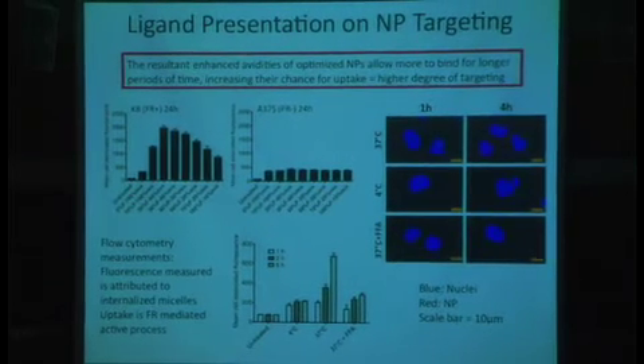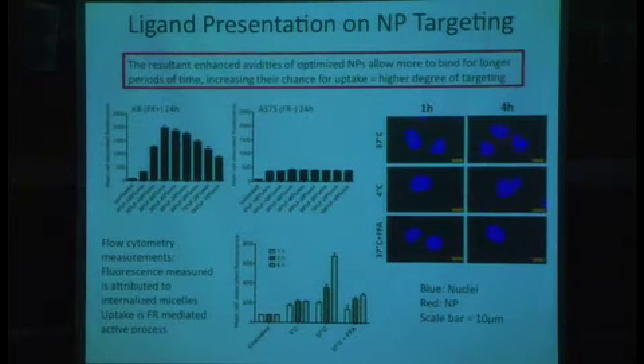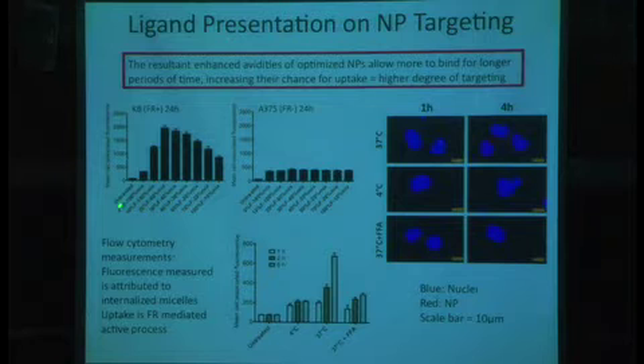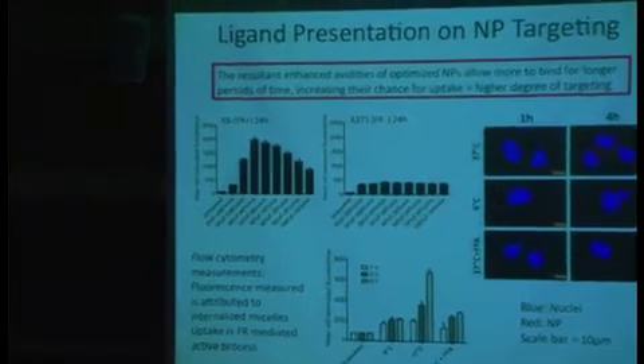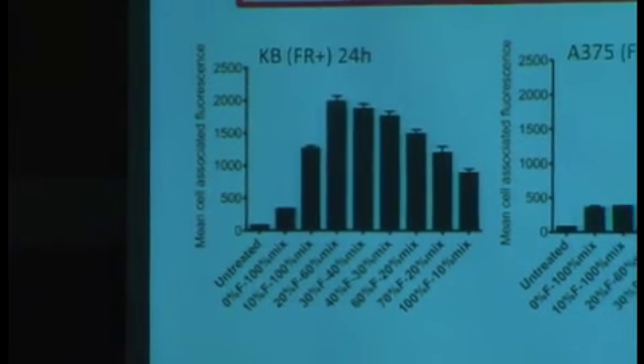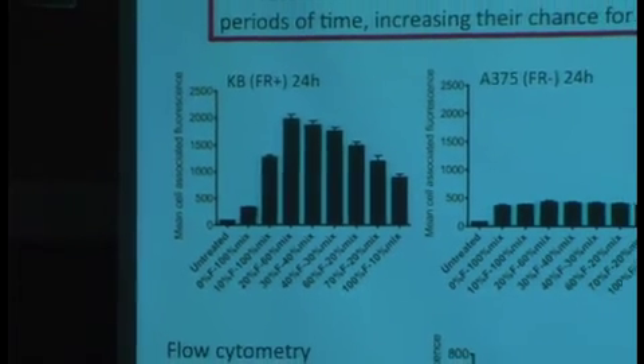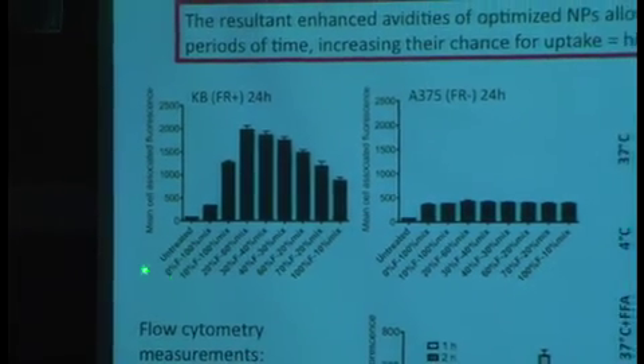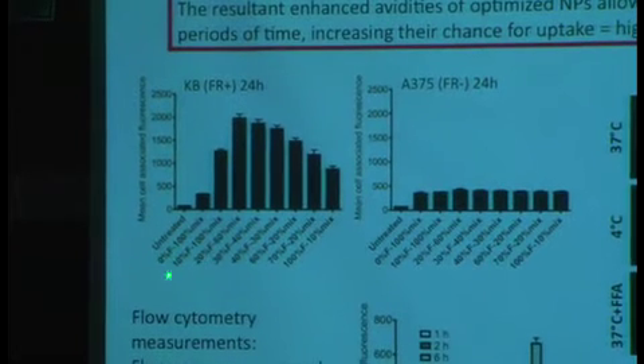We actually designed these systems so that we had cluster sizes ranging from 1 on this G16 dendron out to the full 16 N groups, and refer to that using 0 to 100% functionalization. However, in this particular set of experiments, we varied these so that they were mixed with non-functionalized systems, so that the net number of ligands on the nanoparticle surface was essentially the same, about 2,000 to 2,500 folate groups on average on a nanoparticle surface. So the number of ligands is the same, but the way in which they're presented is different.